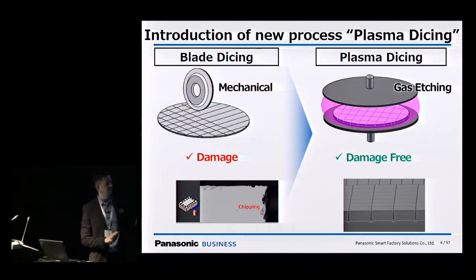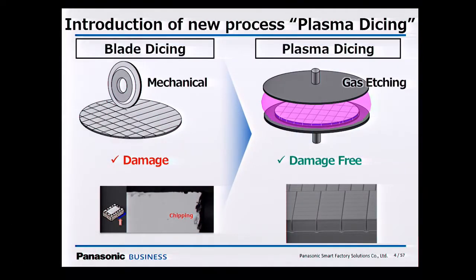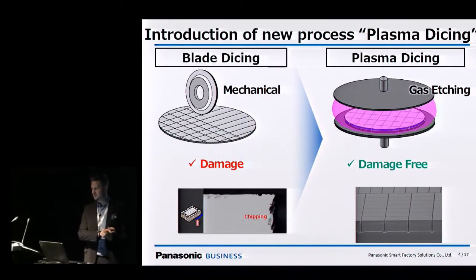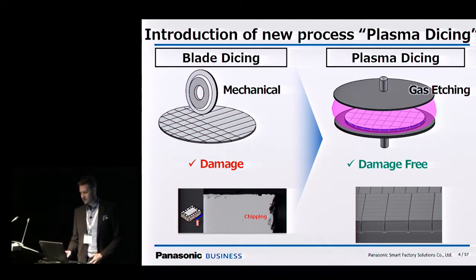So the conventional way of dicing has been with blade and still is with blade. But as you can see on the left, there's a good evidence of the damage it can cause. A new approach on the right is existing dry etching technique, but applied in a practical way on dicing frame with a mask on the wafer, where then you develop the mask or use some other techniques to remove the mask where you want to dice, and where there's no mask, it will be etched. So instead of a line-by-line mechanical process, you can now think about a whole wafer-based process that is applied on the whole wafer.